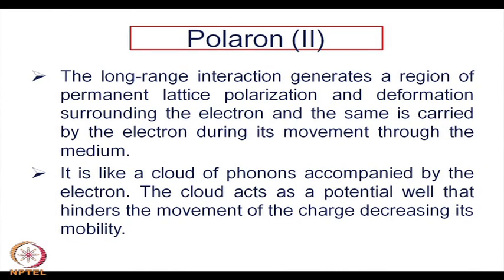The long range interaction generates a region of lattice polarization and deformation surrounding the electron, and the same is carried by the electron during its movement through the medium. More or less the same thing is being talked about. It is like a cloud of phonons accompanied by the electron. So, now we are talking about a cloud of phonons. It is sometimes called a sea of phonons, and that is the lattice vibration, and the cloud acts as a potential well that hinders the movement of the charge,